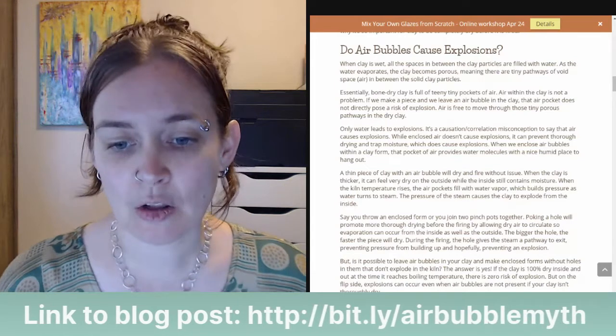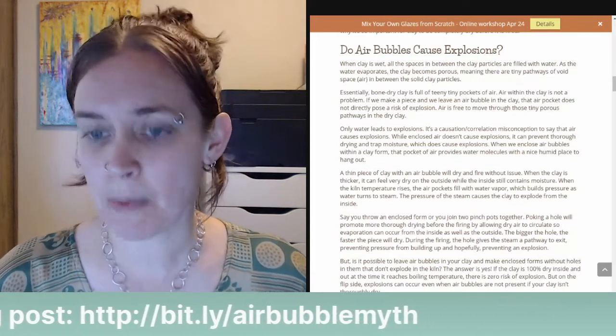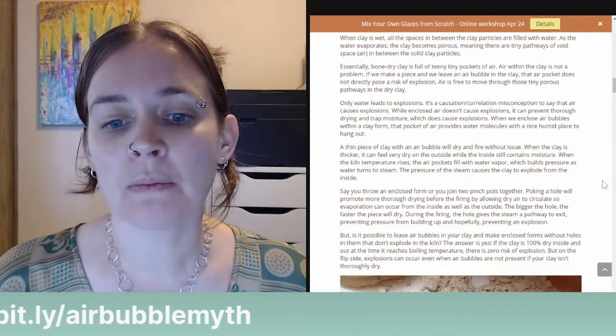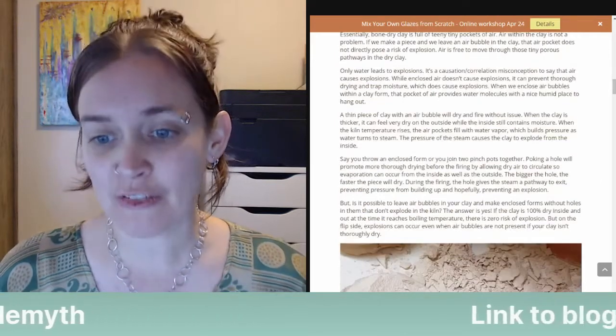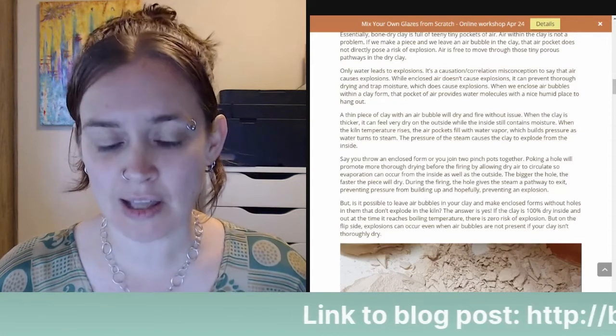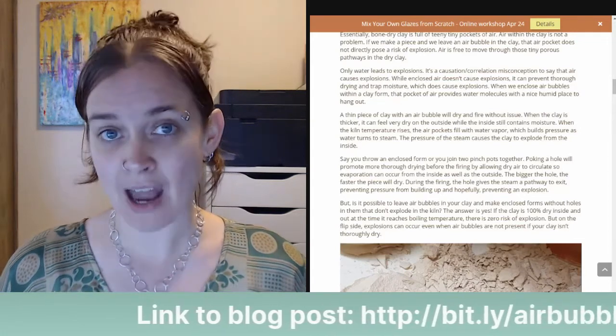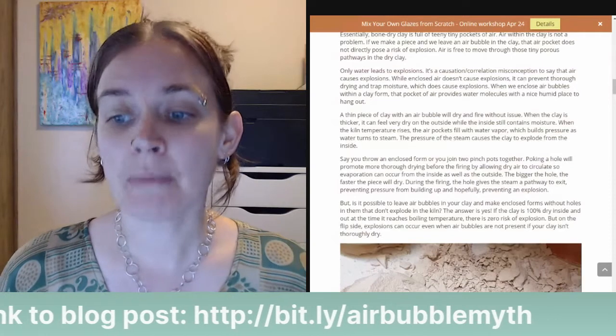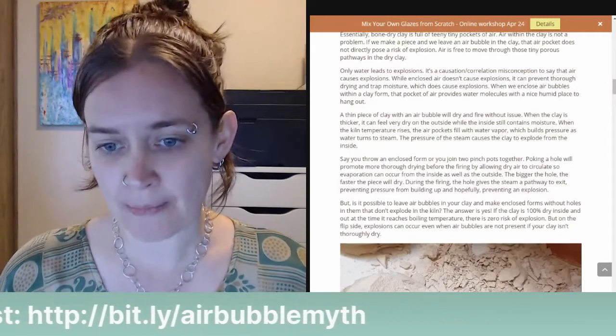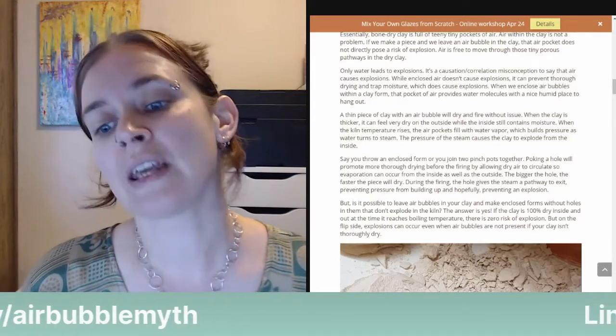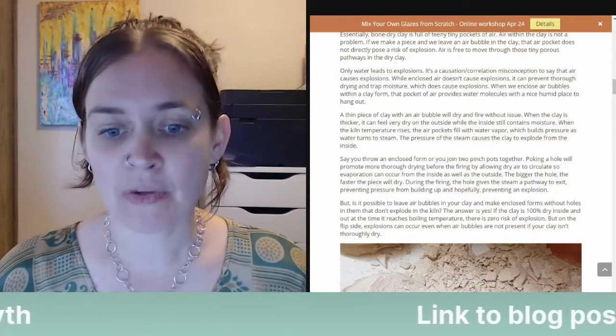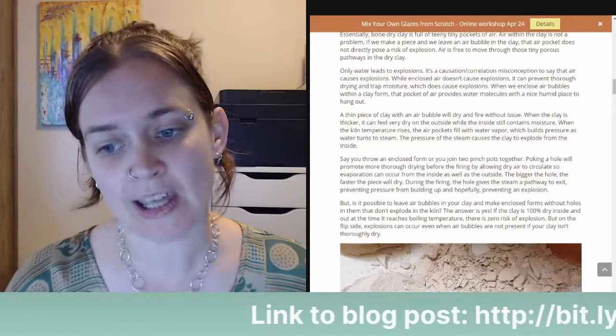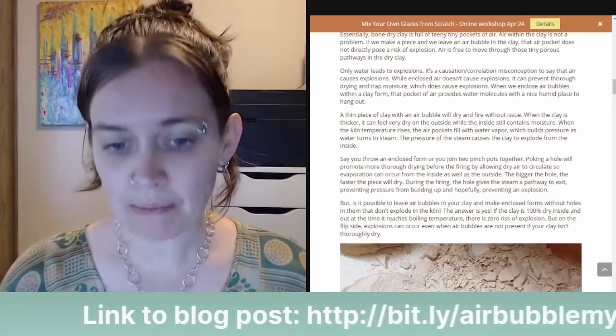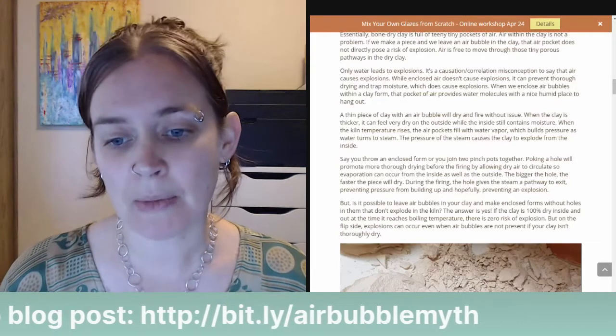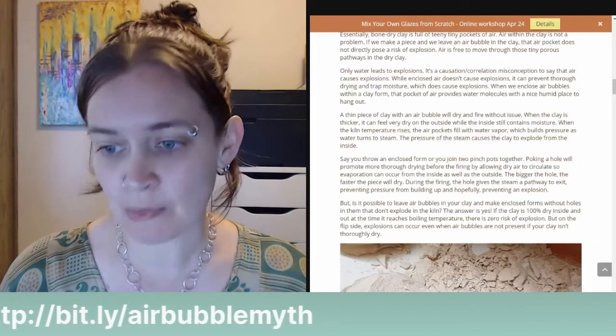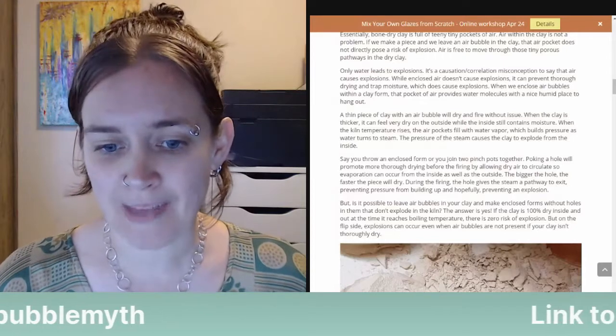Say you throw an enclosed form or you join two pinch pots together. Poking a hole will promote more thorough drying before the firing by allowing dry air to circulate so evaporation can occur from the inside as well as the outside. The bigger the hole, the faster the piece will dry. During the firing, the hole gives the steam a pathway to exit, preventing pressure from building up and hopefully preventing an explosion. But it is possible to leave air bubbles in your clay and make enclosed forms without holes in them that don't explode in the kiln.